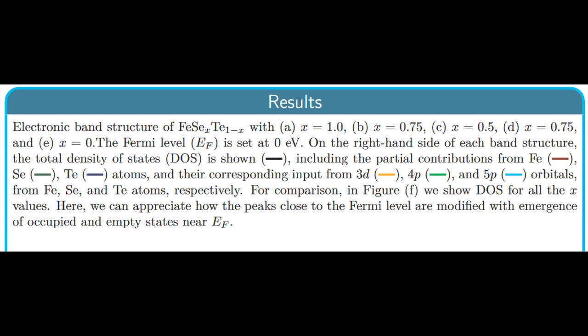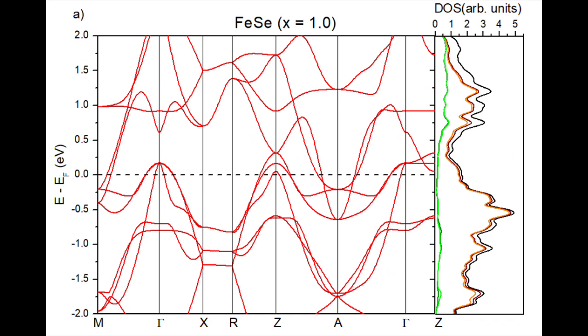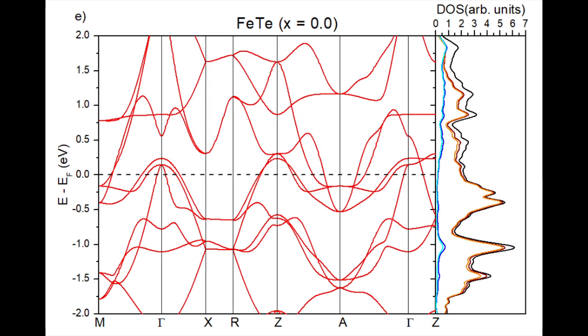With the computational details previously described, we have obtained the next results captured in these graphs, which present the electronic band structure on the right hand and the density of states on the left hand. In graph A, we have a limit case, X equal 1.0, the iron selenium compound, while in graph E, the other limit case, X equal 0.0, the iron telluride compound. This shows a similar energy dispersion in the first Brillouin zone, exhibiting a pair of differences like the breaking of degeneracy at the gamma point in iron telluride, and an increase of localization of states in the gamma path as X diminishes. This change can be appreciated gradually in the other graphs.